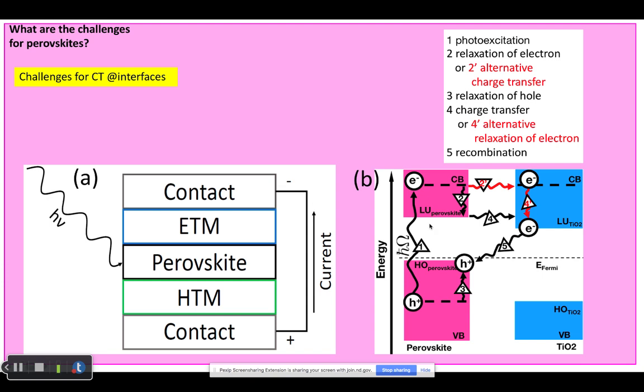So in the favorable alignment of bands, a photoexcitation, number one, results either in relaxation of the electron in the conduction band or charge transfer to the conduction band of the interfacing titanium dioxide. And then, upon this relaxation, due to the difference in potential, the electron will anyway jump to the titanium dioxide, and the lowest excitation will be a charge-separated state where the hole stays on the perovskite and the electron resides on the titanium dioxide. So the question for research is to investigate, first, if the morphological parameters of the simulation cell affect alignment of bands. Second, if morphological parameters affect the height of the barrier and couplings and the ability of the electron, the rate at which it transfers.